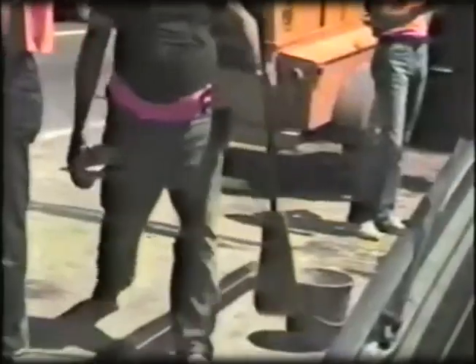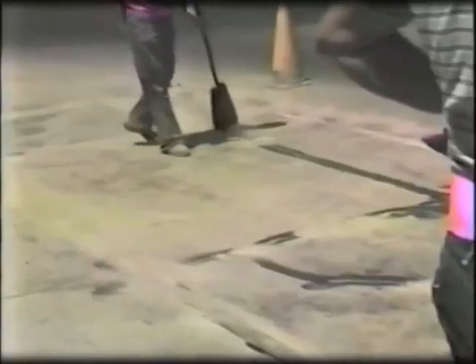A V-shaped squeegee can be used to scrape excess sealant into the slot. This reduces sealant waste and leaves the cured sealant flush with the road surface, or even slightly below the surface where it is better protected from traffic. After sealing the slot, a light dusting of Portland cement may be added to prevent tracking out if the surface of the cured sealant is still tacky.